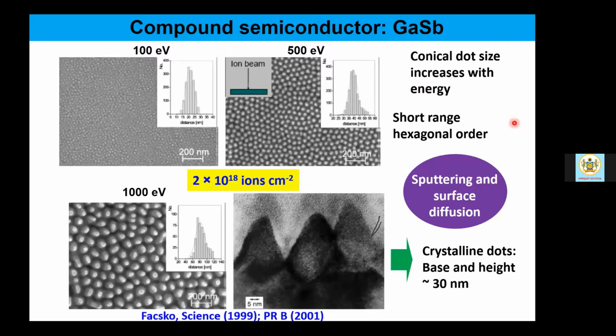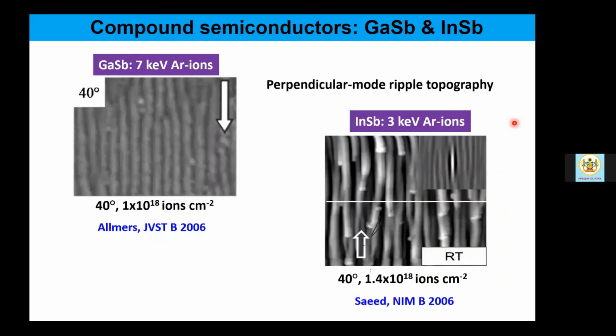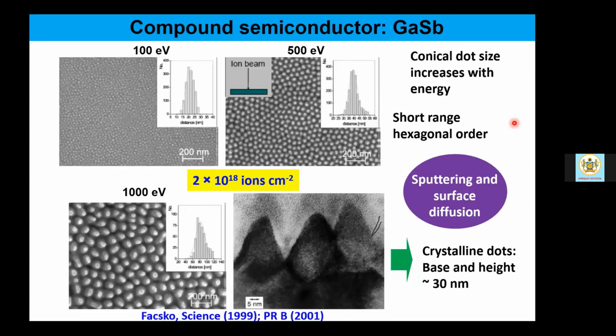And so it's two competitive processes, mostly ion sputtering and ion-induced surface diffusion, that give rise to such pattern formation, and that is the common belief by now after 20 years. And you see various patterns. Again, gallium antimonide is not restricted to only dot patterns. These are all at normally incident ions.